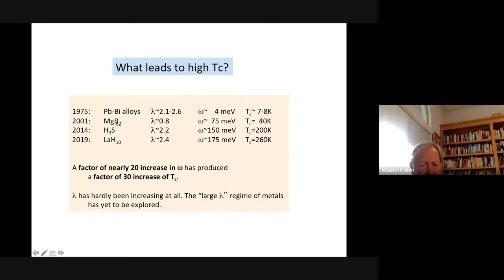2001, magnesium diboride was discovered. The frequency scale goes up by a factor of almost 20. TC went up to 40. But lambda is only about 0.8. If lambda had been 2 here with this frequency, TC would have been much larger. 2014, hydrogen 3 sulfide, lambda 2.2 calculated. These are all calculated numbers, except these alloys. The frequency scale is 150 millielectron volts, and TC is around 200 Kelvin.